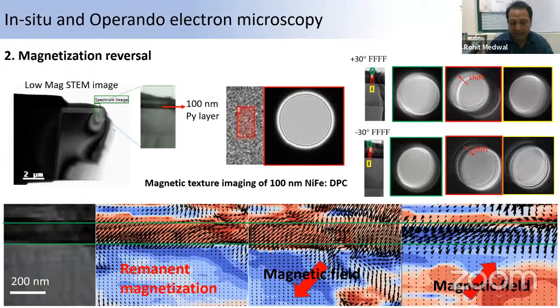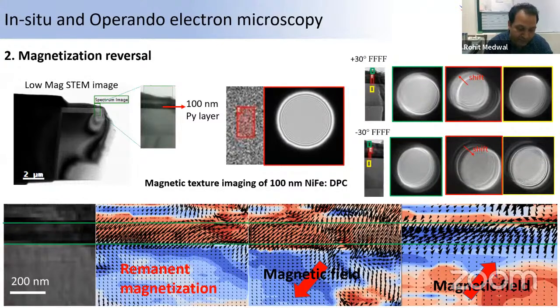And when we did the analysis, this analysis is also a bit tricky. We have a special code in Python that we designed so that we can map this magnetization based on the shift of this bright-field disk from one direction to another direction. And we can see that from one direction we can map the direction of magnetization, which is in this direction. Maybe I'll just take the pen. So you can see the direction is this direction. And after applying the magnetic field in this direction, we can see that the direction of the magnetization is in this direction. So we are able to successfully demonstrate that.